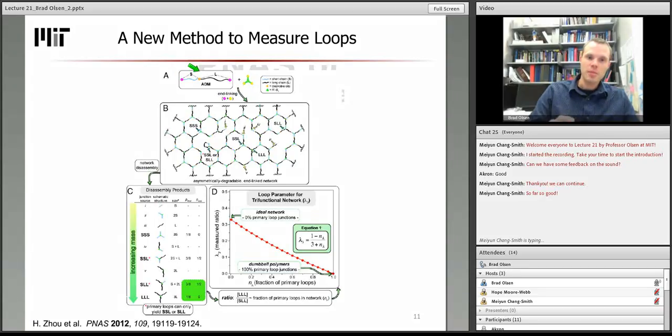And depending upon the type of network junction, essentially depending on how many of the chemical groups react at the trifunctional group, and whether there are loops or bridges, there's a different probability of having combinations of short and long ends going into that junction. And so essentially you'll see different combinations of long, so he shows here, for example, 3 long ends going all into the same junction cannot happen if you form a loop.